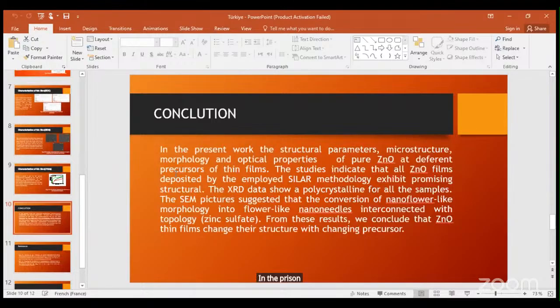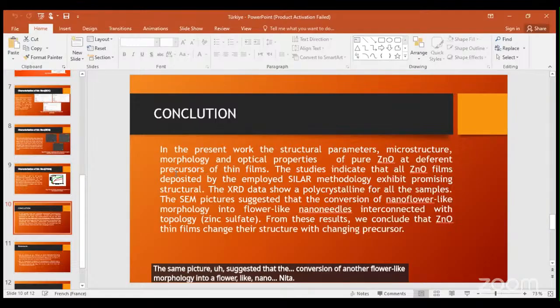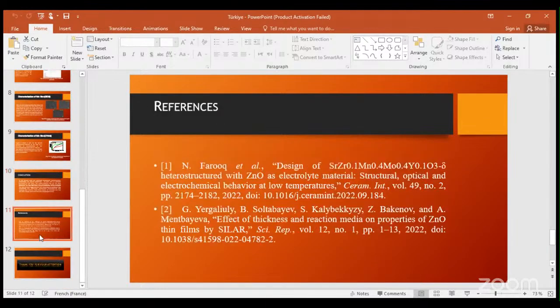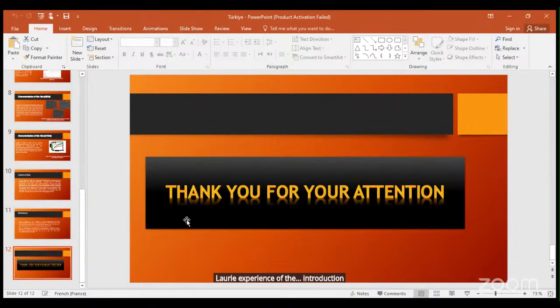In the present work, the structural parameters, microstructure, morphology, and optical properties of pure ZnO thin films at different precursors were studied. The studies indicate that all ZnO films deposited by the employed SILAR methodology exhibit promising structural properties. The XRD data shows a polycrystalline structure for all the samples. The SEM pictures suggested the conversion of nano-flower-like morphology into flower-like nano-needles interconnected with the topology with zinc sulfate. From these results, we conclude that ZnO thin films change their structure with changing precursor. The references are listed at the end of the presentation, and thank you for your attention.